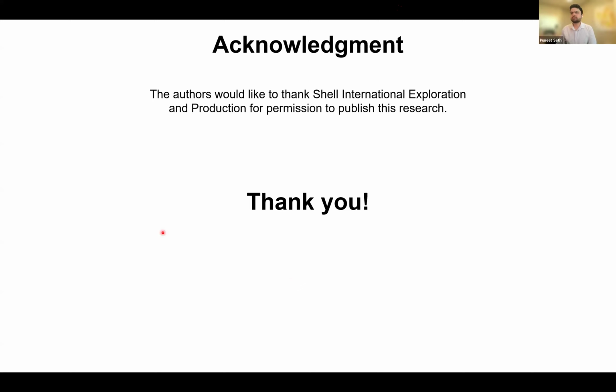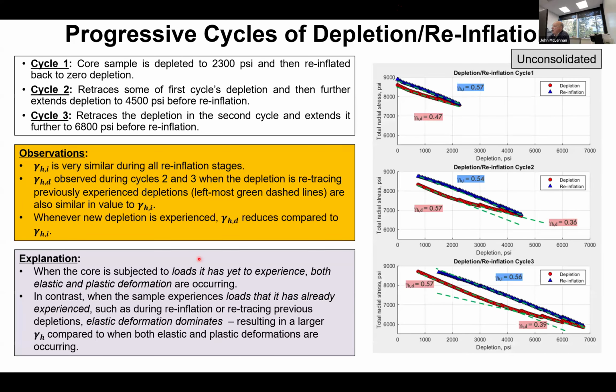Ed Siebritz has been asking whether in the cyclic depletion lab tests, cycle 1 depletion also looks nonlinear, so it would be good to break it into two slopes. That's right. Good point. Yes, it is curving. This would have been quite a soft sample, and you're depleting to, let's say, 2300 psi, and you see that curving. So maybe it was elastic up to maybe this point or so, and then the plastic deformation started dominating, and that's why it does that. So good point. We maybe should have separated it out.